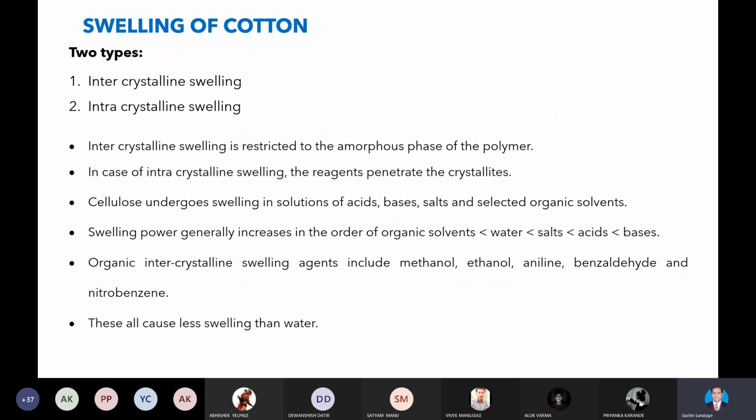During the practical we have seen that when you carry out the treatment of cotton with 5% NaOH at a boil, we get swelling. Similarly, when you treat the cotton with 17.5 to 22.5% NaOH, there is swelling, because of which the kidney-shaped or bean-shaped cotton gets converted to an elliptical or round shape. All this is happening because of the swelling.